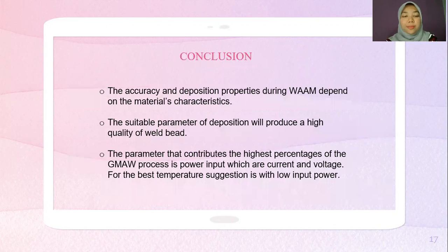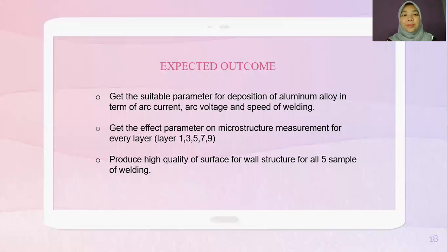As a conclusion, the accuracy and deposition properties during wire arc additive manufacturing depend on material characteristics. The suitable parameter of deposition will produce a high quality of weld bead, and the parameters that contribute the highest percentage of the gas metal welding process are power input, which are current and voltage. The best temperature suggestion is with low heat input power.